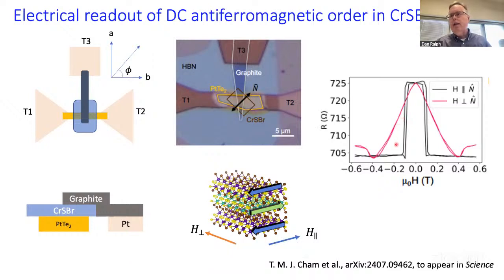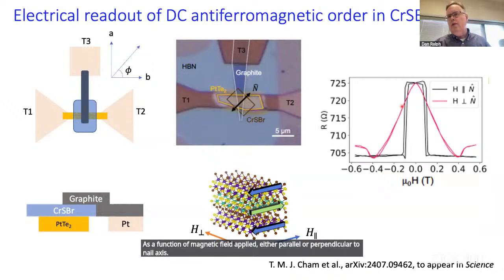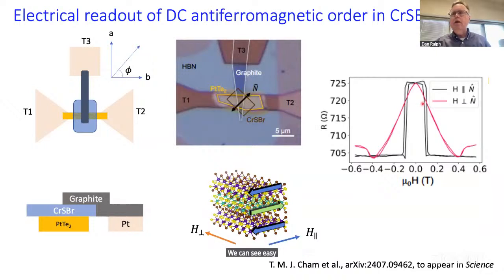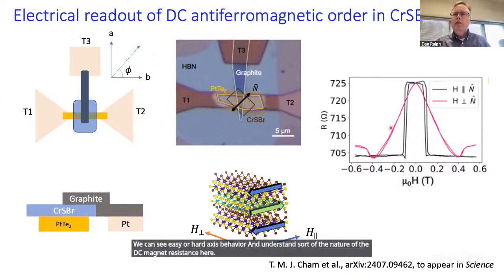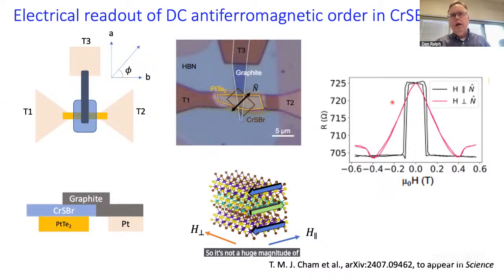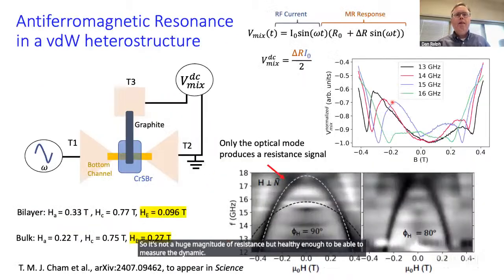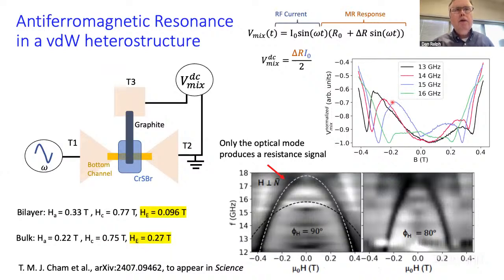As a function of magnetic field applied either parallel or perpendicular to the easy axis, we can see easy or hard axis behavior and understand the nature of the DC magnetoresistance here. So it's not a huge magnetoresistance, but healthy enough to be able to measure the dynamics. Okay. So to probe the dynamics, we use a variation of the spin torque antiferromagnetic resonance technique.